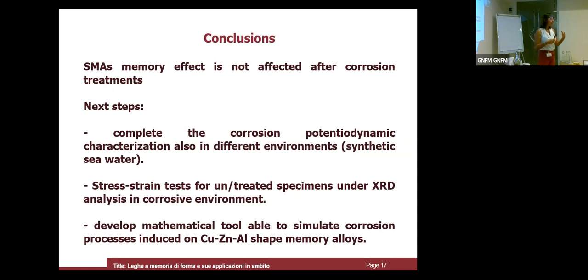In our model, we start from these models, and we would like to have corrosion parameters. The final aim is to understand how the corrosion affects the shape memory. In our samples, we cannot see any effect on the shape memory, so the shape memory is guaranteed with our tests. But it's important to understand how the corrosion can affect the shape memory, because these elements are used for civil protection, so the applications are really wide. So it's important to better analyze the effect of corrosion in structural activities. One part that is missing for us is to evaluate stress-strain tests.